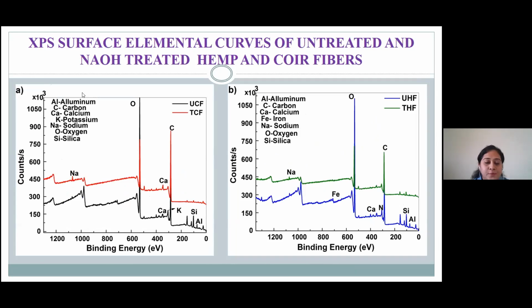We have also done the XPS surface elemental characteristic curves - X-ray photoelectron spectroscopy curves, which help give the surface elemental composition. UCF is the untreated coir fiber and TCF is the treated coir fiber. The untreated and fiber reinforced AAB soil samples were molded into pellets and then oven dried before the samples were analyzed.